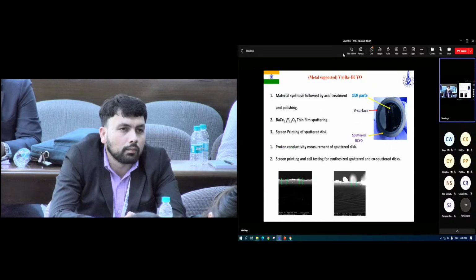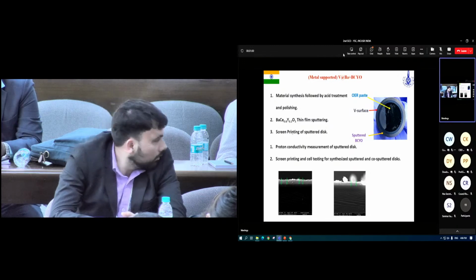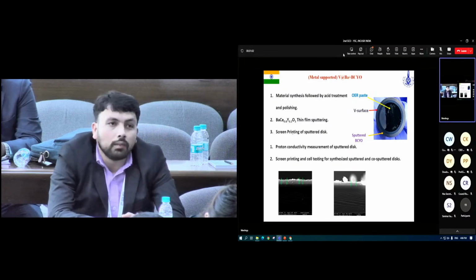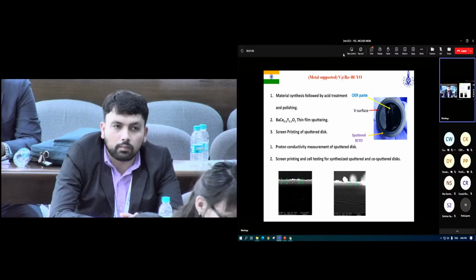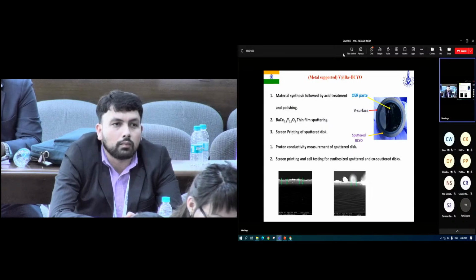Then this is the metal supported cell, where we used vanadium metal as the anode in place of nickel oxide, versus the anode supported cell where we used nickel oxide and electrolyte. Here we only use vanadium at the anode, and then this barium cerium yttrium oxide is the electrolyte, and the same OER paste is the cathode.